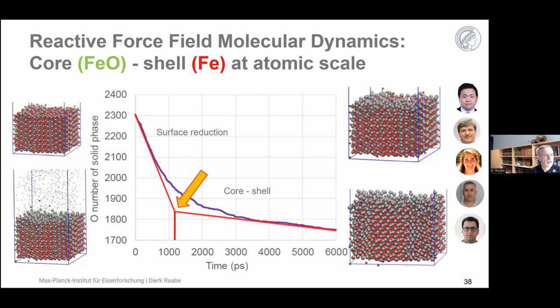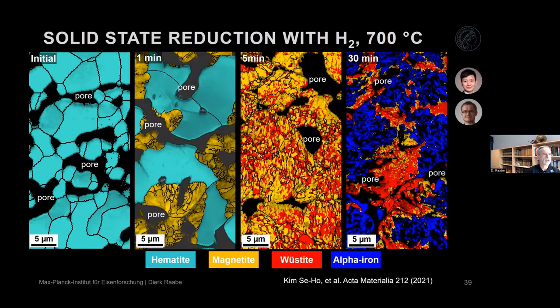So there's a lot of development room on the theory side to do simply much better potentials, which for iron oxide, due to their magnetic nature, is of course also quite challenging. And currently, a couple of projects pursue that, for instance, by machine learning enhanced bond order potentials and similar types of approaches. And of course, we also do DFT calculations with the theoreticians.